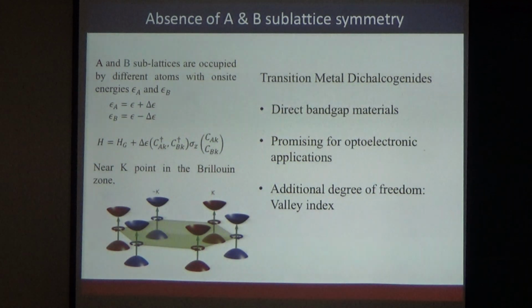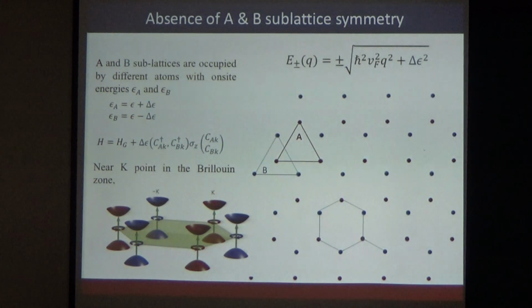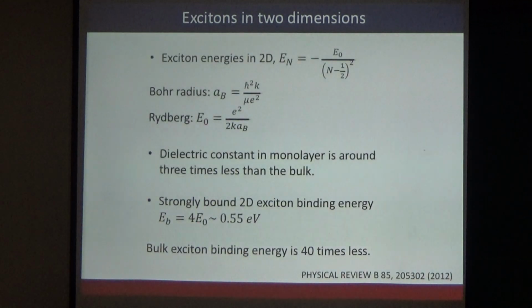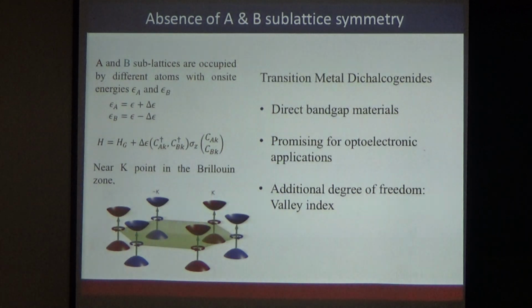And it is very interesting that, if I consider a bulk material made of the same atoms, we will see that this will not happen, and this direct band gap will no longer be valid. People have observed, and this is well established, that if you go to bulk, then electronic excitation is very difficult to make, so it will not emit light. So if I excite it by shining light or by any other means, it will not produce any light. But if it is a direct band gap, what you can do is excite the electrons in the valence band into the conduction band, and then it can form electron hole pairs. So they will interact with Coulomb interaction in 2 dimensions in the plane of this material, and that will form a hydrogen-like system, right?